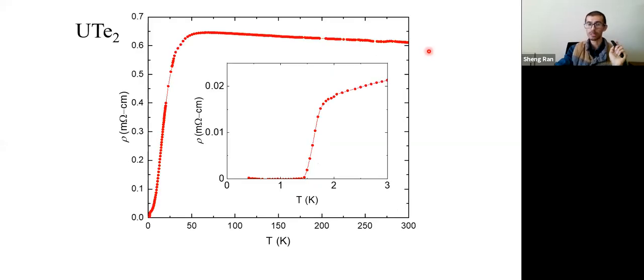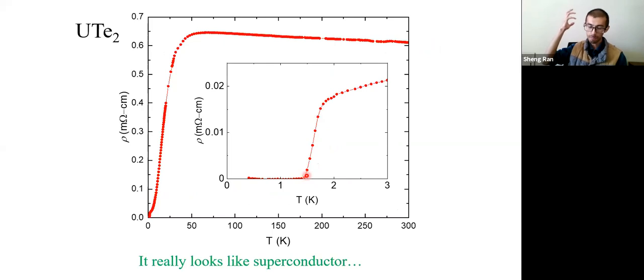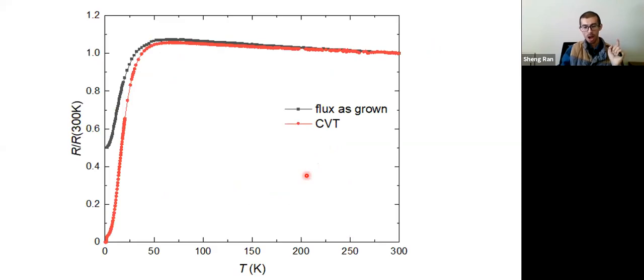Okay, let's measure resistance. Here I'm showing resistance as a function of temperature. You can see below 1.5 or 1.6 K, the resistance goes to 0. Indeed, this is a superconductor. So I was looking for a magnetically ordered state, and it turns out we got a superconductor. Well, one thing already indicated the superconductivity is unconventional.